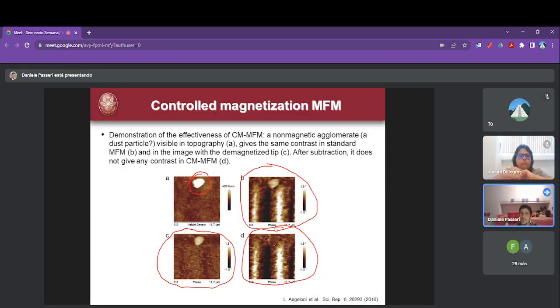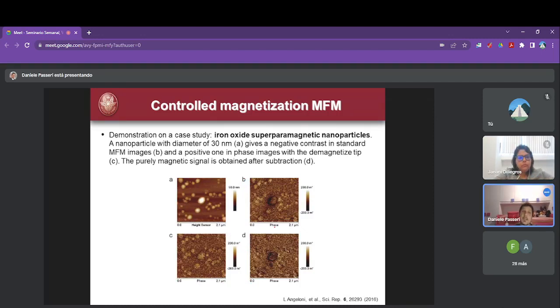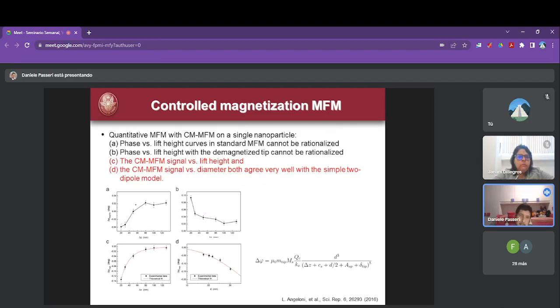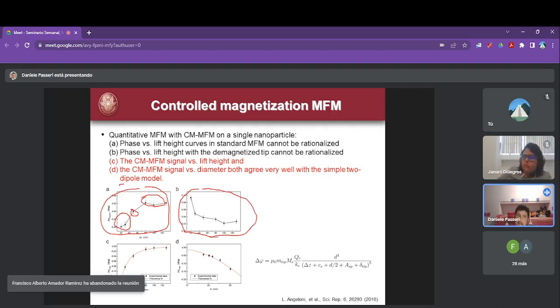Okay, for this case of the floppy it is not interesting at all, but it is much more interesting in the case of nanoparticles, because again, we have the topography, the standard magnetic force microscopy, the image with the demagnetized tip. You see all the nanoparticles are bright as expected, and this is the subtraction. And we understood that this was good because if you consider the quantitative phase, this is the standard magnetic phase. Basically, this is meaningless. You see, the beginning is dark, then it's bright, here it is almost zero. This is the electrostatic image. If you take this one and you subtract this one, you obtain these dots.